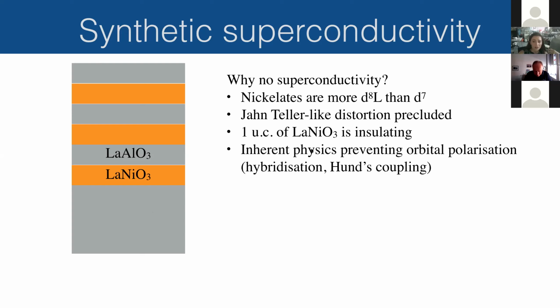And of course, the inherent physics might just be preventing orbital polarization from fully happening. And this could be just because nickel really does not want to be orbitally polarized. It would rather be in a high spin configuration with an extra electron in the out-of-plane orbital than be low spin with two electrons in the in-plane orbital. So no superconductivity like that.